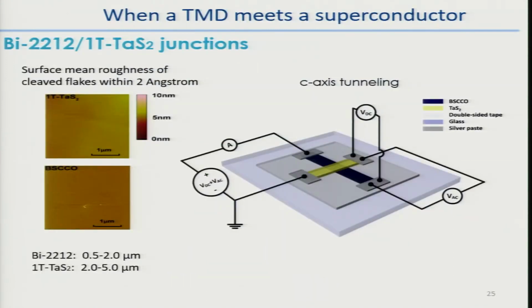Okay. I hope you all are convinced that we're seeing CDWs at the interface. You can ask me later. But what happens when a transition metal dichalcogenide meets a superconductor? And as I said in the introduction, BSCCO is cleavable and acts in many ways as a very beautiful surface. You can cleave it, and we can just press our tantalum disulfide against BSCCO. We made 4-terminal devices where the tantalum disulfide is in the yellow. It's placed on top of the BSCCO flake. It's not as beautifully sculpted as this picture is, but we get a tunnel junction, and we can measure it in 4 terminals. And these are AFM pictures of the quality of our surface, at the order of fractions of a nanometer flat.